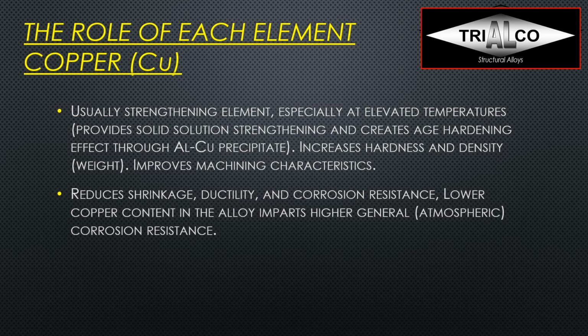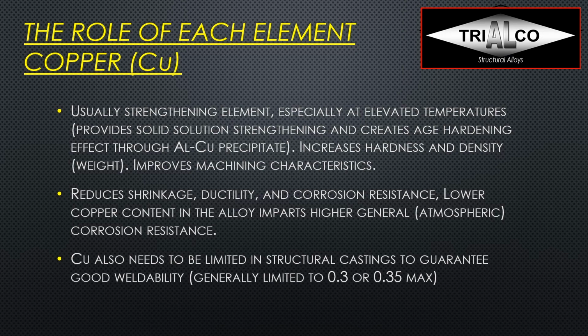That's why it is usually a problem in the 300 series for any application that needs to be corrosion resistant, and is therefore minimized. Lower content means it imparts higher general atmospheric corrosion resistance. Copper also needs to be limited in structural castings if they are welded, because as soon as you go beyond 0.3 or some would say 0.35% copper, you get into trouble when you try fusion welding the parts.